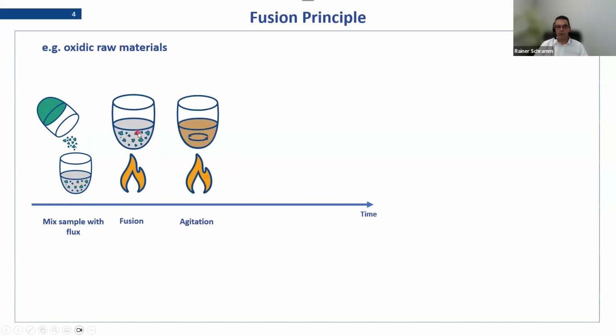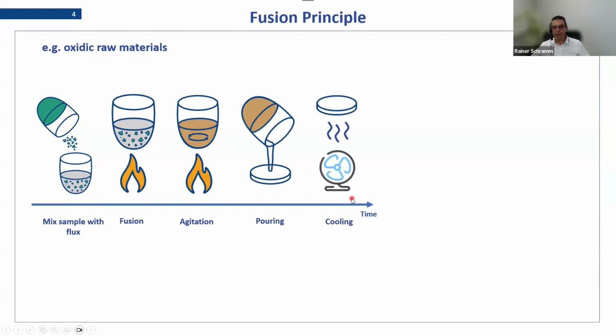Once it's all getting liquid, then the liquid has to be agitated, and in the moment it's homogeneous, you could pour it into a preheated mold, in expectation that the glass is also homogeneous in the end. And last but not least, finally, you have to cool it down to avoid any cracking and to also get a stable homogeneous glass. So if we now look where the weighing steps are in this procedure, then of course we have to weigh a sample and we have to weigh the flux, and both result in a dilution factor. So it's not only the weights of the sample and flux, it's also the dilution that counts.